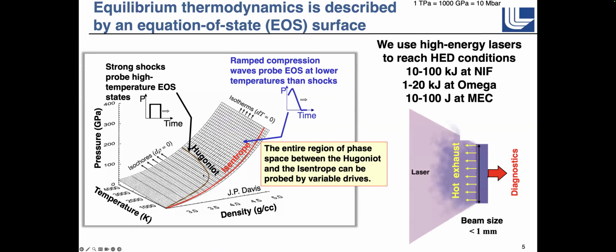Here's a very simple P-T-rho equation of state. This is of aluminum, I believe, and John Paul Davis at Sandia made this a number of years ago, but I think it's a really nice way to talk about things. So if you were in a diamond cell, say at room temperature, you would be essentially following an isotherm up this path, and you would get to the same temperature, so you're just compressing. You could also do a dynamic experiment where you're taking advantage of the fact that you can send a shock wave moving through your sample.